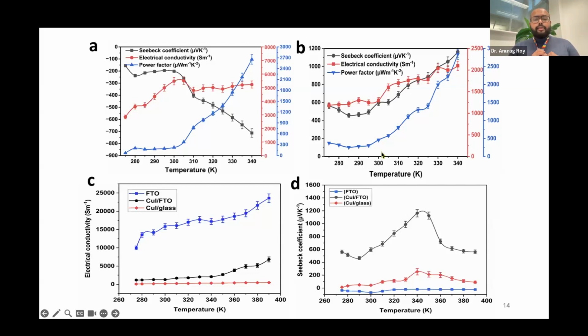And now here, another important thing is the effect of the substrate. As a substrate, we use FTO, fluorine doped tin oxide, the conductive glass. You can see how FTO helps to promote more electrons, and that is why, without FTO and with FTO, there is a drastic and significant change in both Seebeck and electrical conductivity measurement. So the substrate plays a very crucial role. If it is a conductive substrate, definitely there is a high contribution from it.